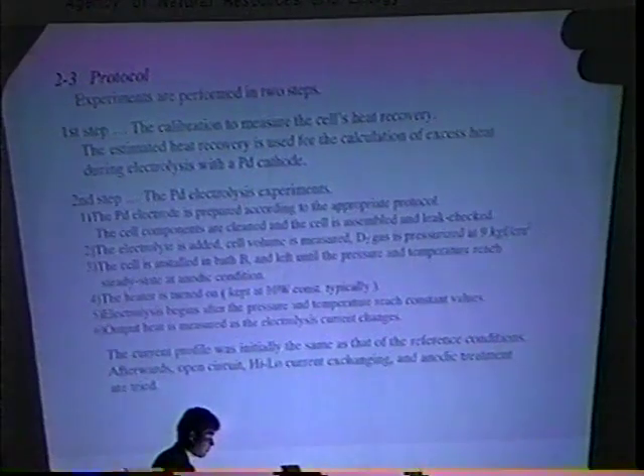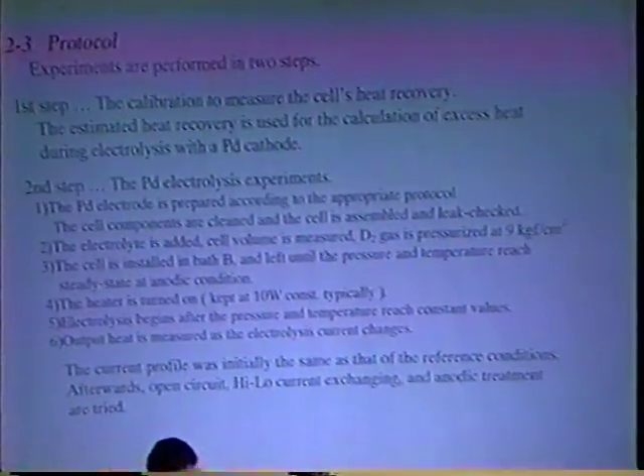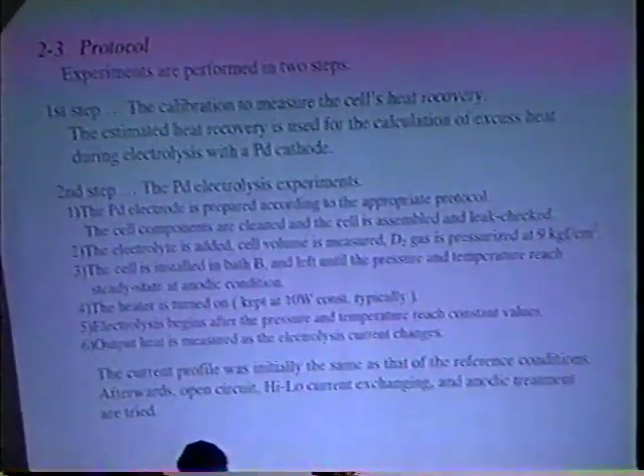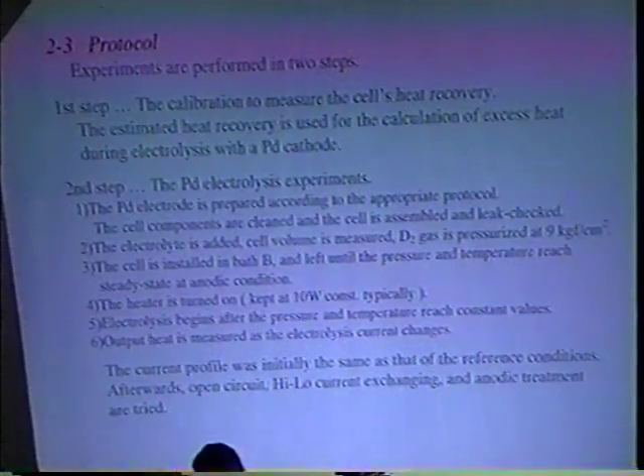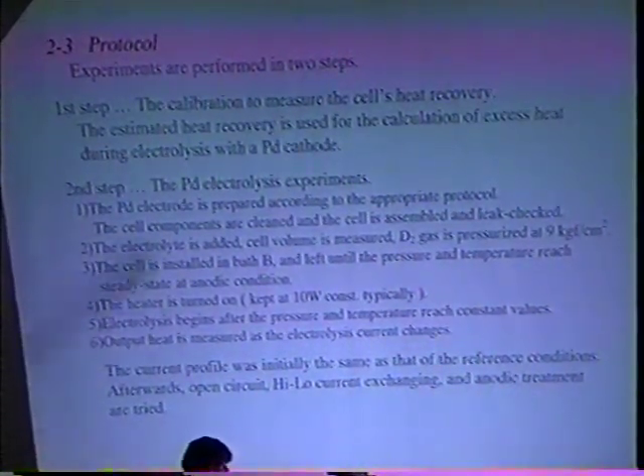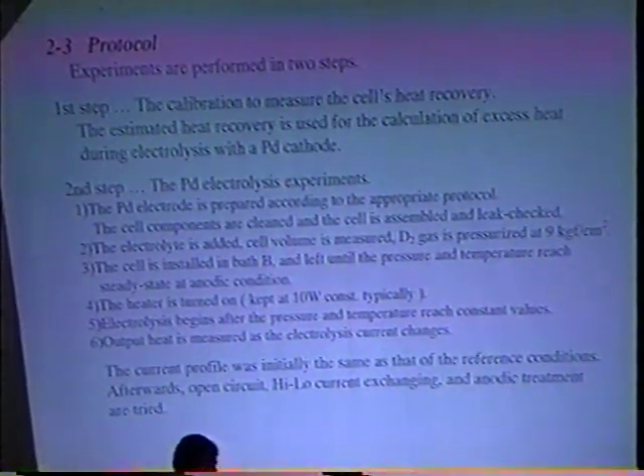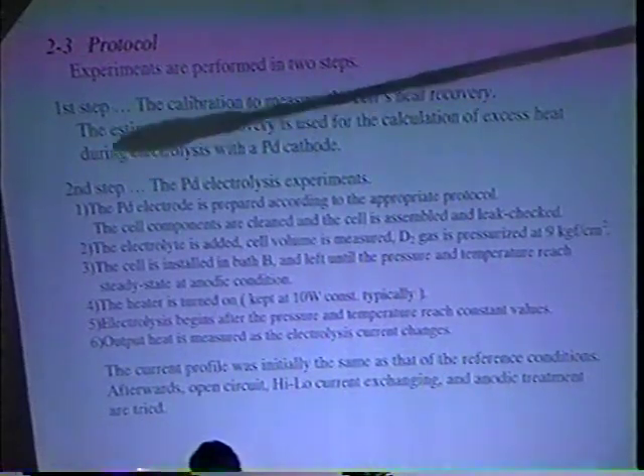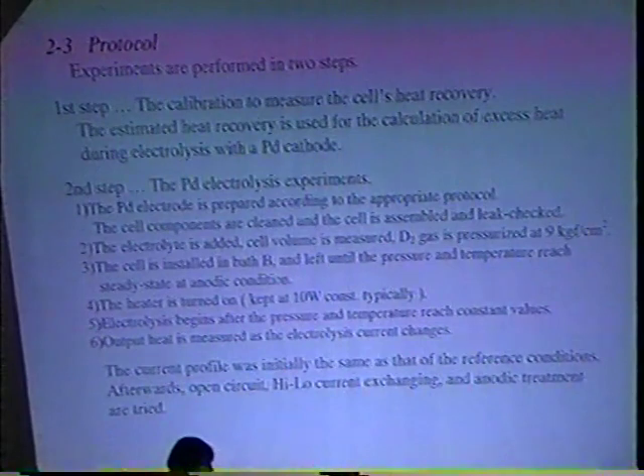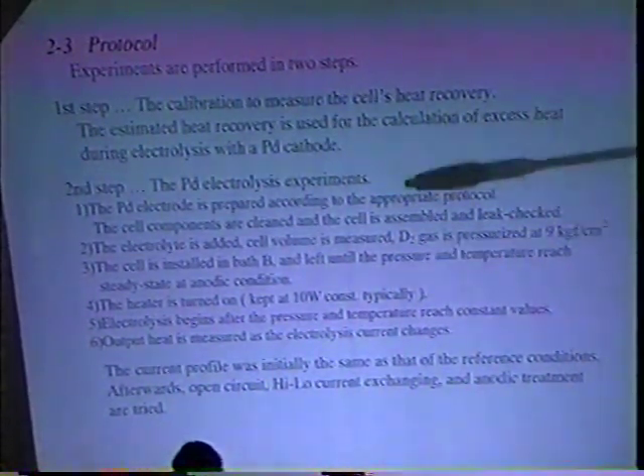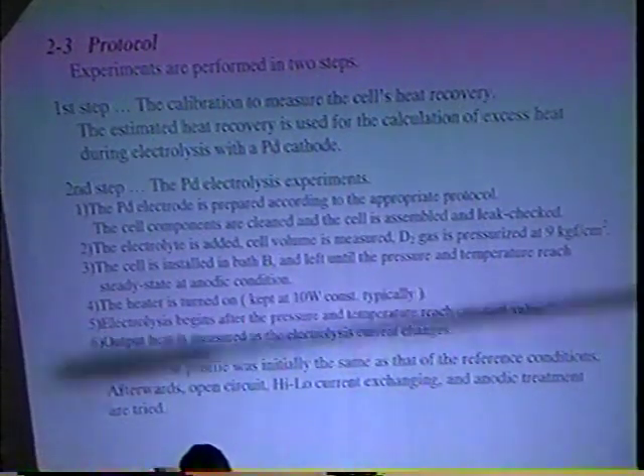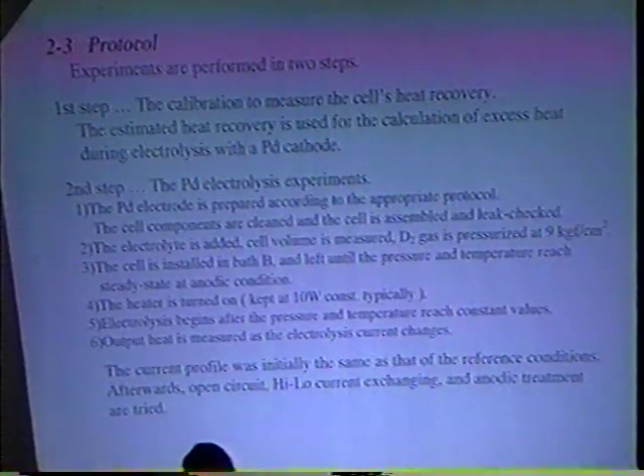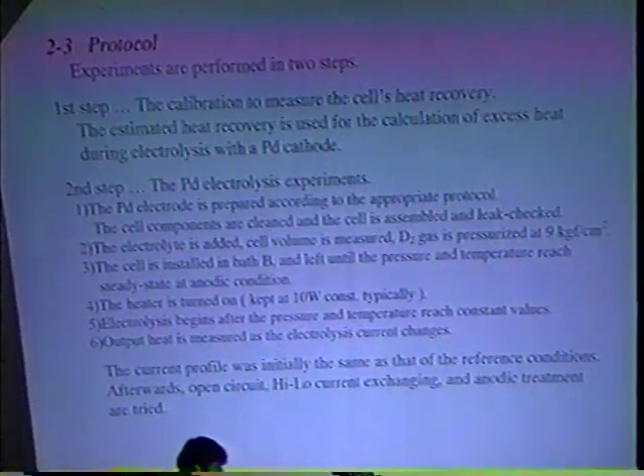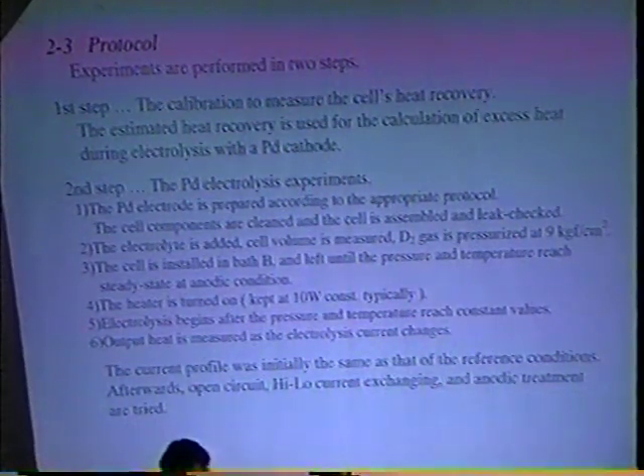Experiments are performed in two steps. First step is a calibration to measure the cell's heat recovery efficiency. The estimated heat recovery is used for the calculation of excess heat during electrolysis with a palladium cathode. The second step is a palladium electrolysis experiment after the calibration according to the following protocol. The current profile was initially the same as that of the reference conditions. Afterwards, open circuit, Hi-Lo current exchanging, and anodic treatment are tried.